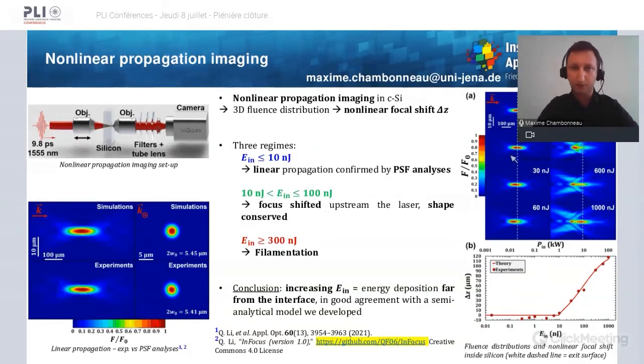Then going back to the data here on the right, for intermediate input pulse energies up to 100 nanojoules, we can clearly see that the focus is unambiguously shifted upstream of the laser. However, the overall shape is conserved. And then when we move to more energy, like more than 300 nanojoules, we are clearly in the filamentation regime, as for instance illustrated here with these focusing and defocusing dynamics. So the conclusion of this data is that increasing the input pulse energy leads to an energy deposition far from the interface, in very good agreement with a semi-analytical model that we have developed.